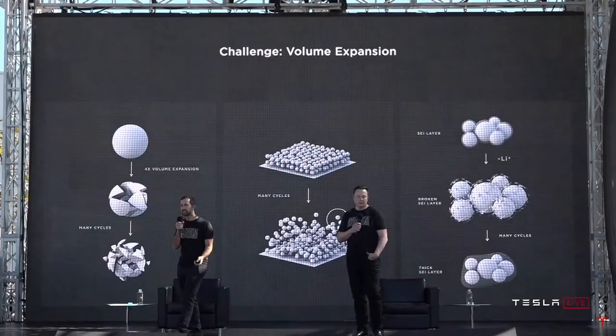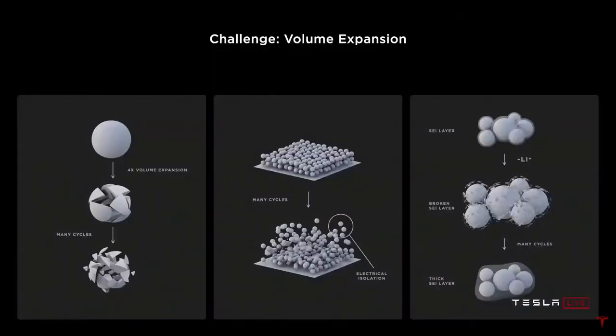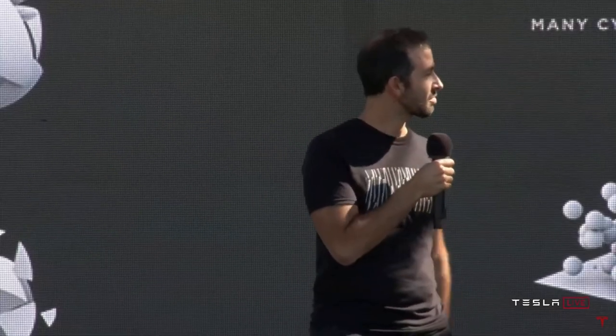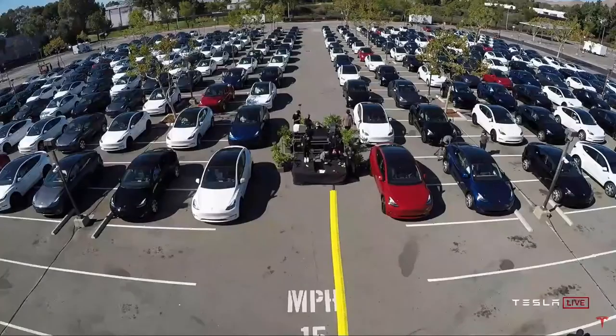The main reason is that silicon expands 4x when fully charged with lithium. And basically, all of that expansion stress makes the particles start cracking, they start electrically isolating, you lose capacity, the energy retention of the battery starts to fade, and it also gums up with a passivation layer that has to keep reforming as the particles expand. Basically, with silicon, the cookie crumbles and gets gooey. That's basically what happens. Good analogy.